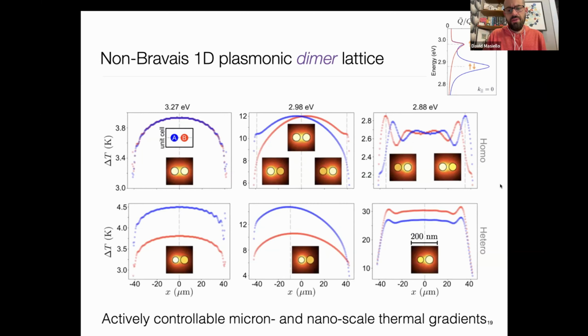Maybe the take-home message here, this is for the homodimer case, the top row, the heterodimer case is the bottom row. This is illumination at the gamma point. And you can see that we're able to engineer thermal gradients not only across, in this case, 80 micron scale of the lattice, but also within the unit cell itself. The unit cell in this case is on the order of a couple of 100 nanometers. And this is all actively controllable. If you tilt the angle of incidence, this is at the gamma point, but if we come off the gamma point, then these thermal gradients are all actively tunable.